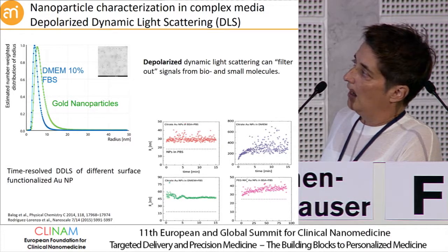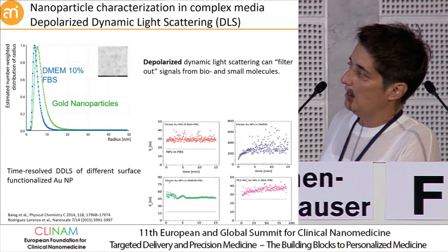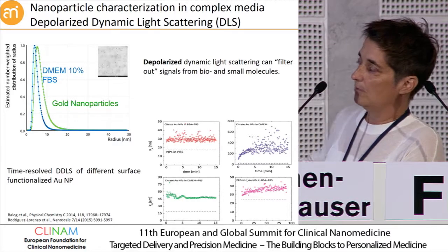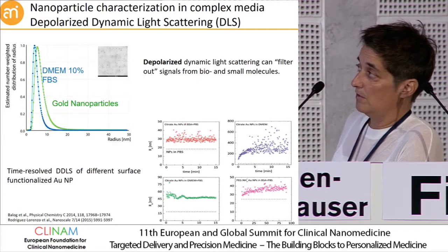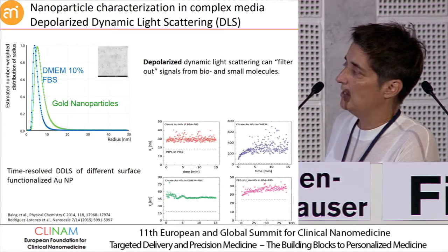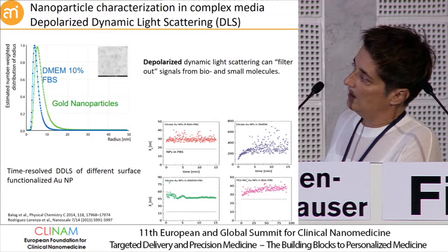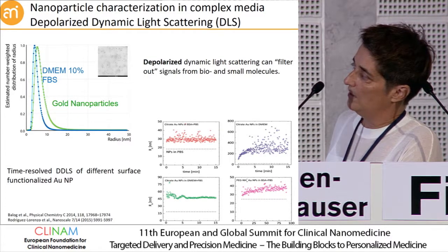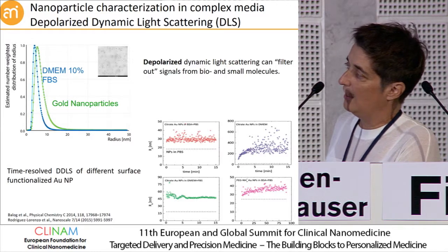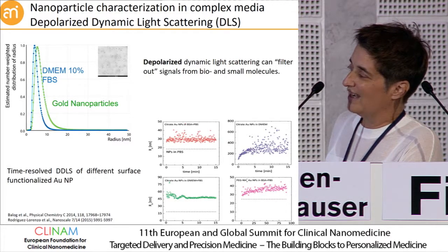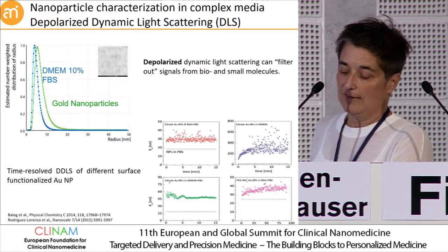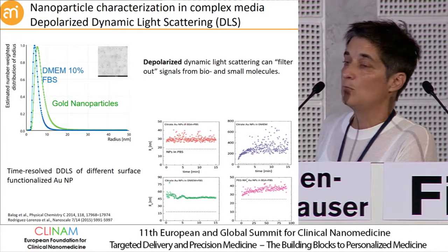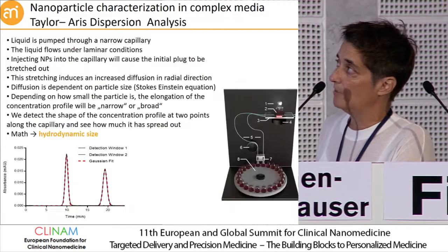And then you put them in different environments. Like here, we keep them in a buffer with BSA. You can see how the particle increases its hydrodynamic size just because it adsorbs the BSA on the surface. You can see that in cell culture medium, within 5 minutes, they strongly start aggregating. If you add serum components, they can be stabilized. This actually works very nicely with some of the particles in this depolarized mode.